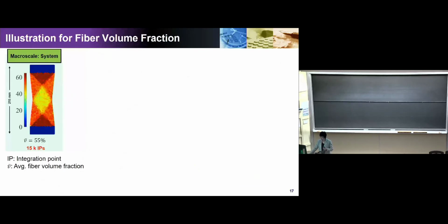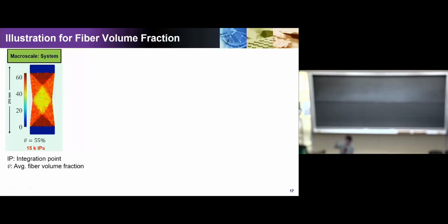So just to illustrate why this is very computationally expensive, imagine that you have a specimen. Right now we're just using a simple coupon, and our actual physical test is also at this coupon level, okay? So we have physical data related to that. The color represents volume fraction at different locations. On average, it's 55% volume fraction, but the color shows the volume fraction is different at different locations. And the number of integration points here is 15,000.